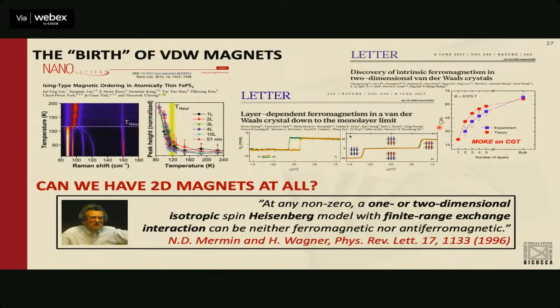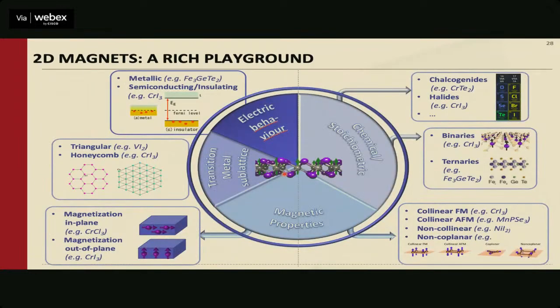But of course, the Mermin-Wagner theorem is certainly valid, but it assumes that the spins are isotropic, right? They behave in the same way depending on where they're pointing to. And it neglects anisotropic effects. For example, from the microscopic point of view, you have spin-orbit coupling in material, the link between angular momentum and spin momentum, which pins the direction of your spin, out of plane or in plane. Anyway, they're not isotropic. So the breaking of isotropy is what allows the emergence of magnetic ordering in these monolayers.